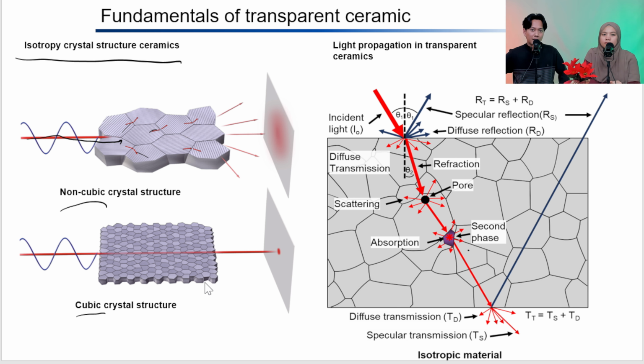It is because the non-cubic structure has different refractive index for different plane orientations. That's just the intrinsic characteristic, I think, of the non-isotropic or non-cubic structure. So for all the orientations, it has different refractive indices. On the other hand, the cubic structure has the same refractive index, just one refractive index for one material. So there is no scattering at the grain boundary, and the light can be smoothly transmitted.